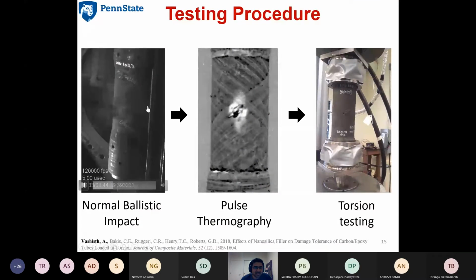We had these small helicopter drive shafts that I made. So we did normal ballistic impact. What that means is there was a bullet that went through the diameter of the tubes. This testing was done at NASA. Then we did pulse thermography to look at the damage in the tubes. This part of the work was done at the Army Research Lab, and the torsion testing of these impacted tubes was carried out at Penn State.